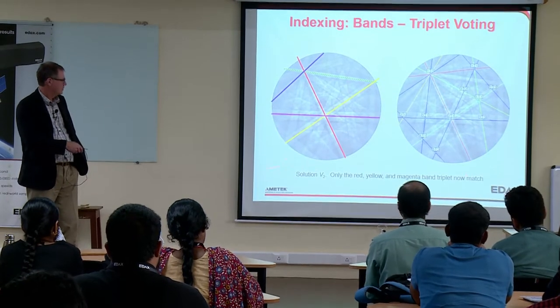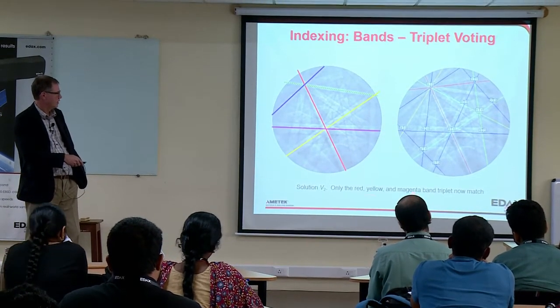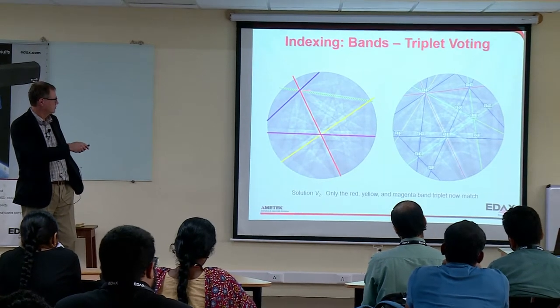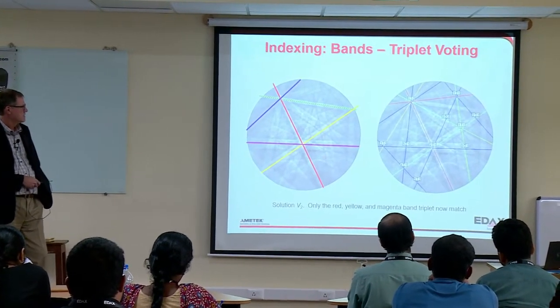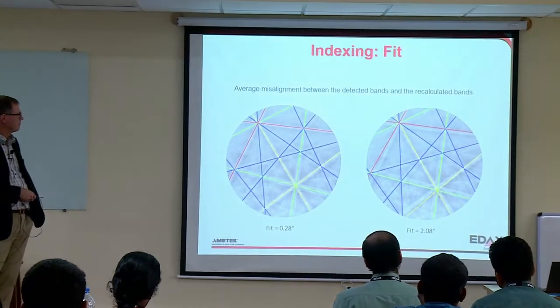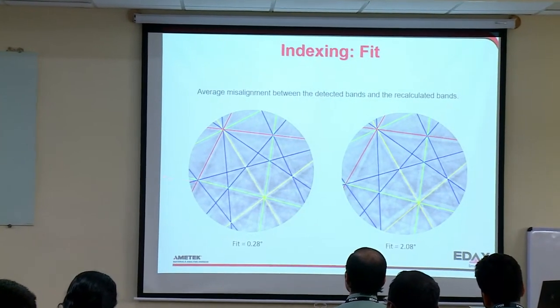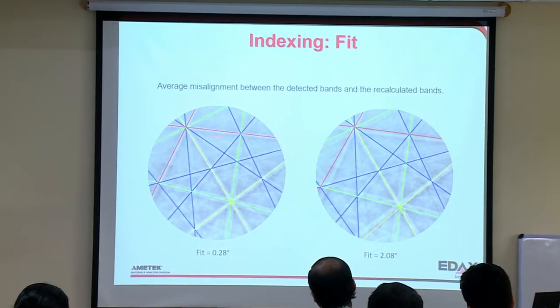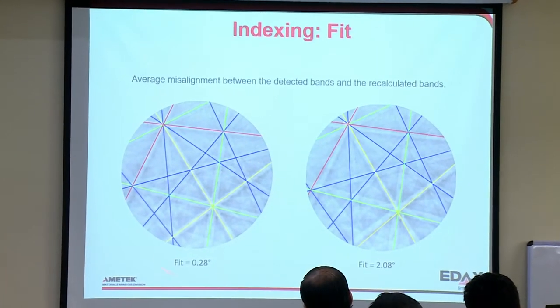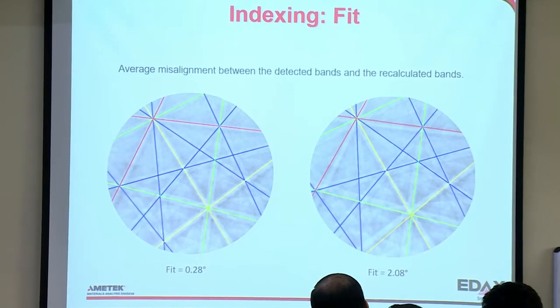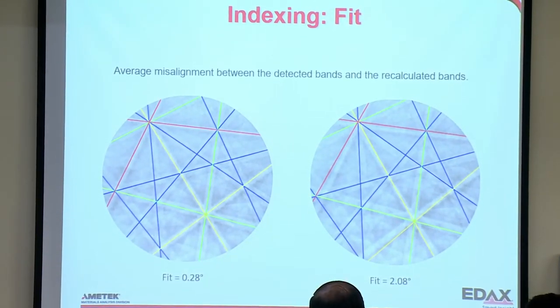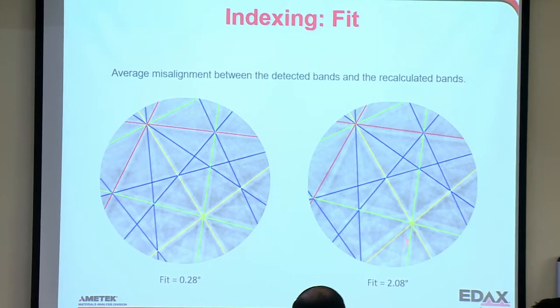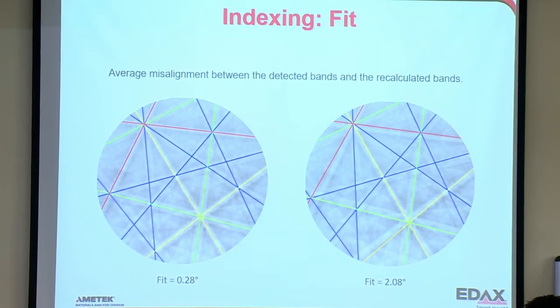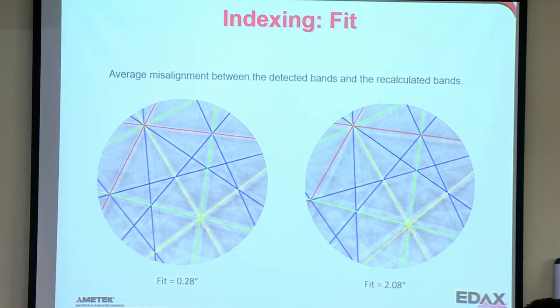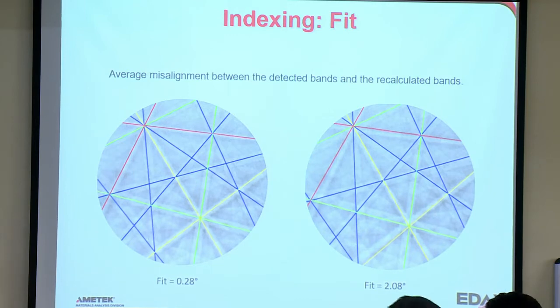This is the second solution here. In this case, only the red, yellow, and magenta bands match. So these 2 do not match. It's only these 3. And so that solution didn't do as well. Now, you can then go back and see how well you match. If the bands match well what we detect, I get a low quality fit, we call it. If the fit is large, that means it's bad. So you can see these bands don't detect very well. And this has to do with how well the Hough transform is working. It has to do with some calibration parameters, which I haven't talked about yet, but we'll get to.